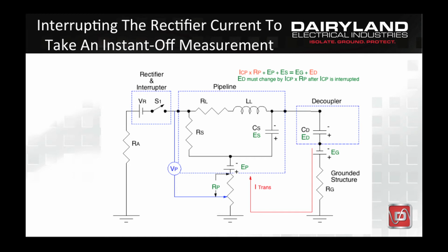It takes about 5 RC time constants for the transient current to fully dissipate and for the pipeline to reach its final off potential. Any measurement taken before this transient current has dissipated will result in an off potential measurement that is excessively electronegative because there will still be an IR drop error component that is being caused by this transient current flowing through R sub P.